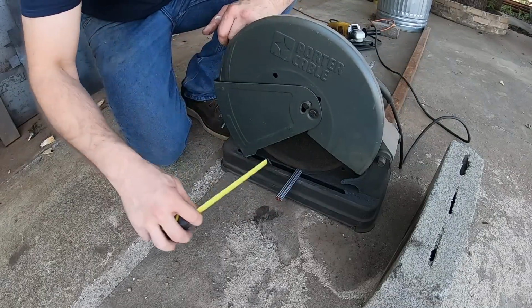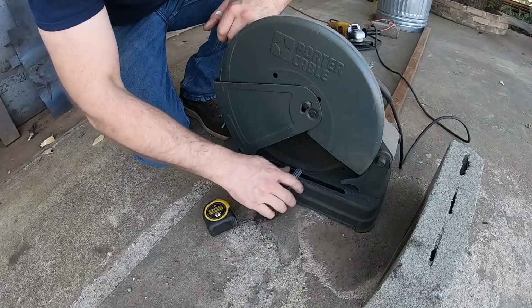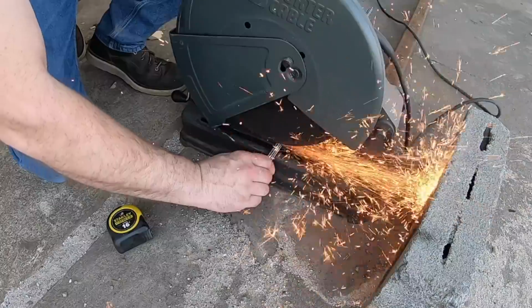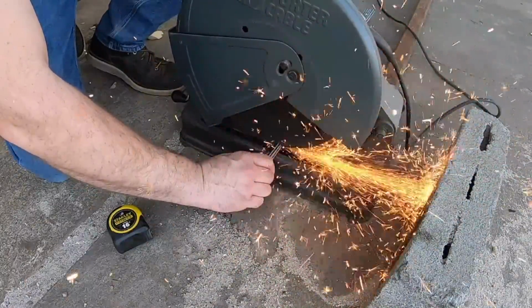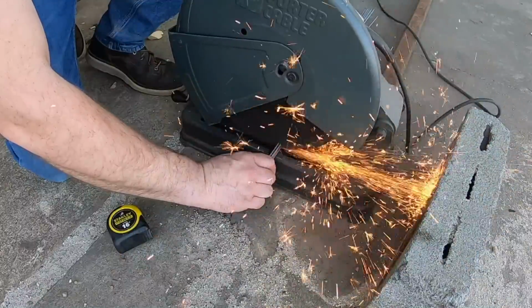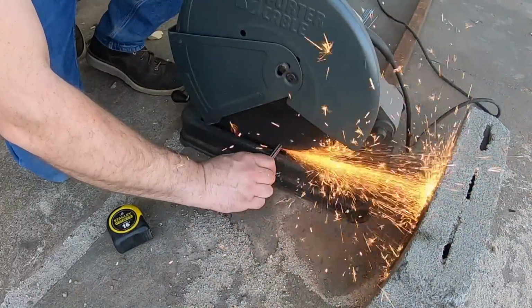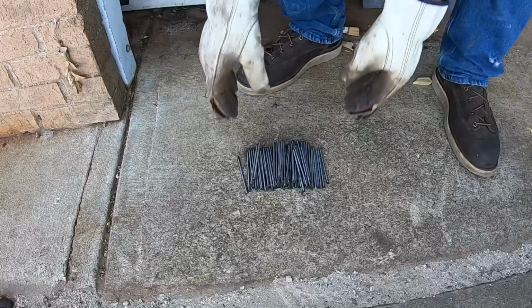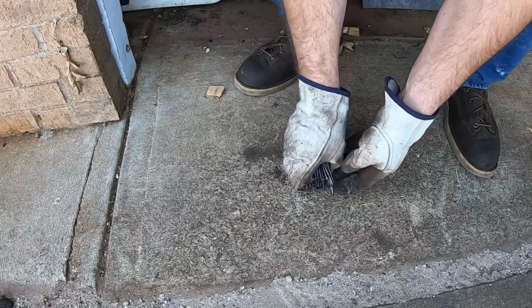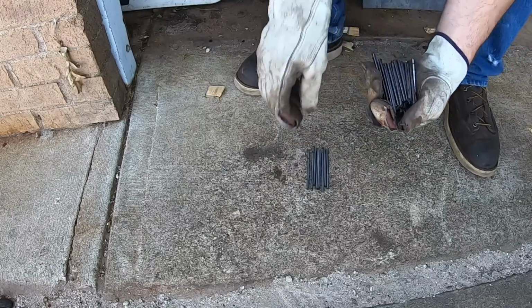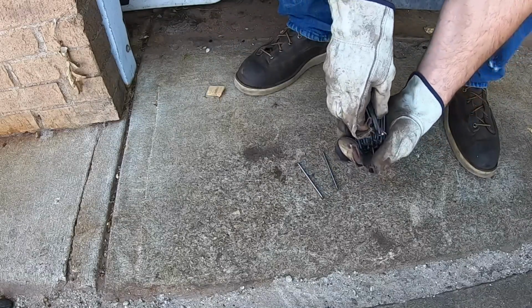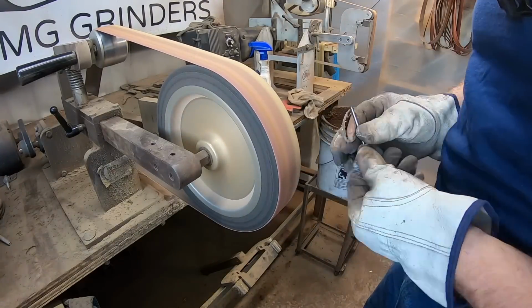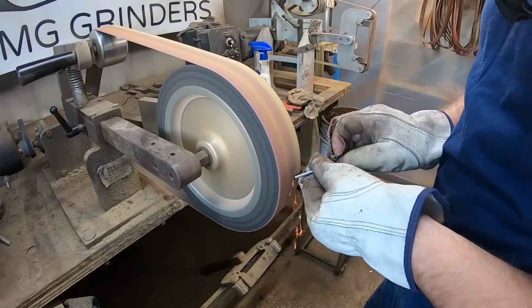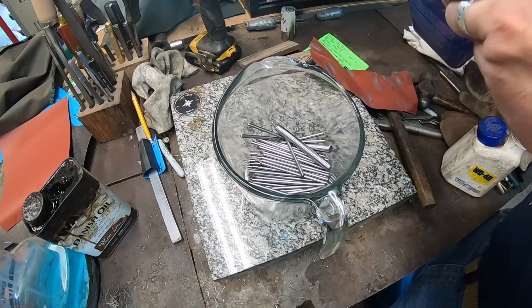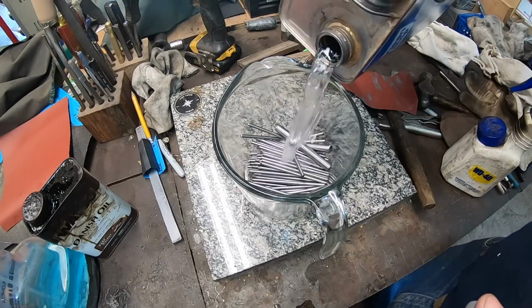This is W1 high carbon steel rod. Now it comes nice and clean, but I went ahead and made sure that the surface was free of any kind of corrosion, anything that would inhibit a forge weld. Sprayed it down with WD-40, chopped them up into pieces, and then painstakingly deburred each one on each end.